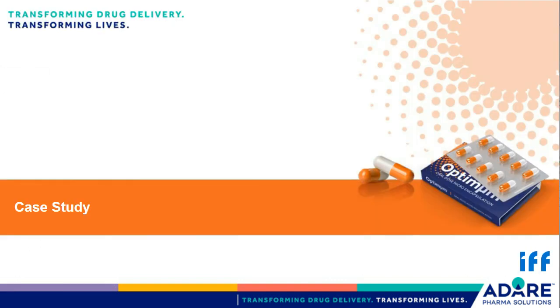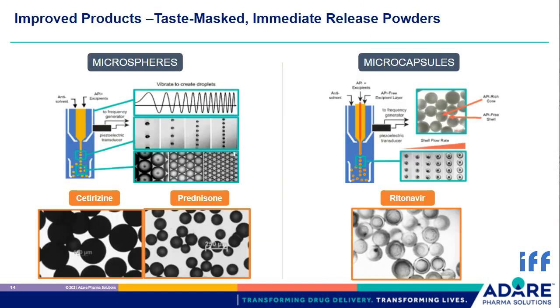I'm presenting now a selection of case studies where Optimum has been successfully applied. Here you have some examples and case studies of both the particle configurations Optimum can design, matrix and core shell. Highly bitter or bad-tasting molecules, such as cetirizine, prednisone, and ritonavir, can be processed using the Optimum technology, leading to tasteless particles having a diameter in the range of 100 to 200 microns.